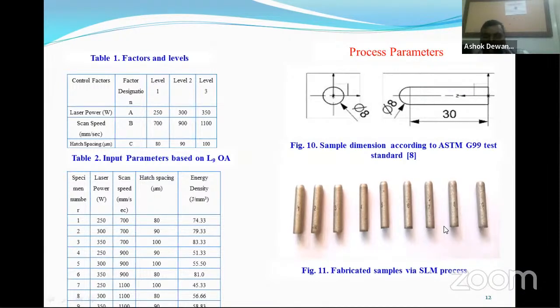These are the process parameters and their level values, which have been taken with the help of past research. So we have adopted an L9 orthogonal array according to the Taguchi design of experiment, and we designed these 9 experiments, and each experiment has resulted in 5 specimens. So there are 9 experiments, and each one is repeated 5 times. So overall, 45 specimens were fabricated.